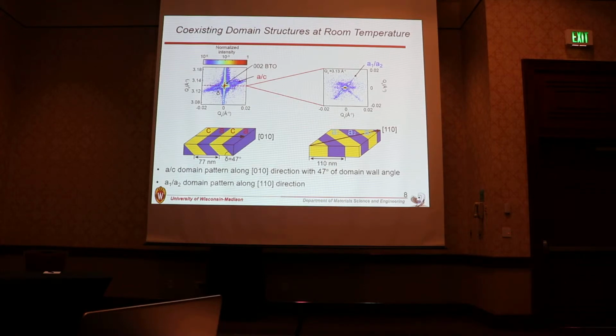And also by taking a look at the QX, QY plane, we can see the domain diffuse scattering from the A1, A2 domain pattern arise around the barium titanate reflections. This also arises along the 110 direction or -1 direction, and it means that the a1/a2 domain patterns align along the [110] direction, and we have obtained 110 nanometers of periodicity. We found that the domain wall in the AA domain pattern is perpendicular to the surface.